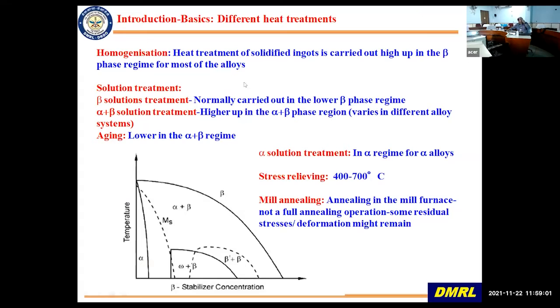Now I'll just introduce some of the heat treatments that we know. First is the homogenization heat treatment, which is normally done to all the solidified ingots. It is heated high up in the beta phase regime, quite high, mostly higher than 1100, to 1200, 1250 or so, to basically homogenize it. That is to basically prepare it for forging and all. And if there is any chemical inhomogeneity, then it also evens out. Time and temperature are decided depending on the alloy and other things.